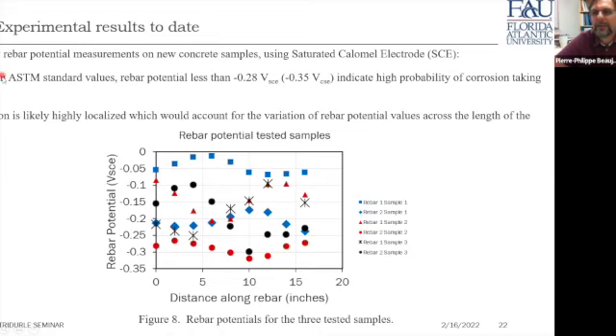So I can read what is actually provided over here. Preliminary rebar potential measurements on new concrete sample using saturated calomel electrodes are leading us to the following conclusion. Based on ASTM standard values, rebar potential less than minus 0.28 V SCE indicate high probability of corrosion taking place. And that is pretty much what is happening in rebar number 2 for sample 2 and sample 3, more or less. In particular, this one right here, the red circle, which would be rebar 2 sample 2.